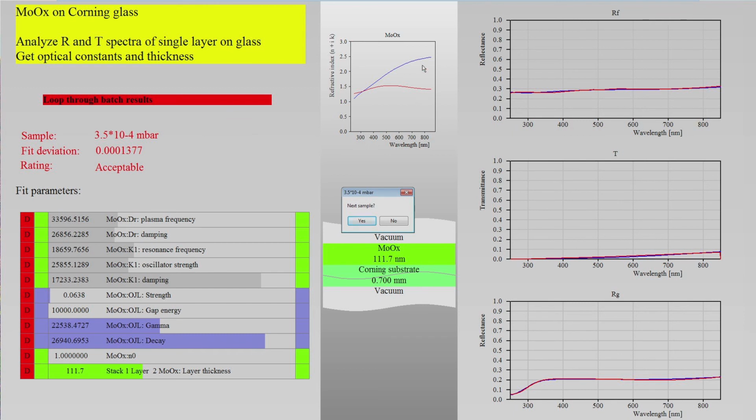And here you see the optical constants. I modeled those optical constants by a superposition of a constant, an OJL model for the interband transition in the UV, a Drude model for the free charge carriers, and in addition, I used a so-called K1 oscillator for this broad feature here in the middle of the visible. It's not really clear what it is.